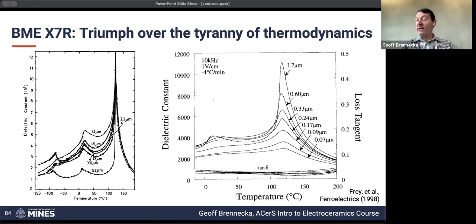But the point is that, yes, we get an increase in permittivity as we reduce the grain size from ginormous down to around a micron. But once we get below a micron, then the relative permittivity starts to drop. And that's essentially because within these really small grains, each grain is only one domain. And so you lose the advantage that in a larger material, you can have multiple domains, and then you get the increased permittivity of having that domain boundary in there that can sort of wiggle back and forth as you apply the electric field.